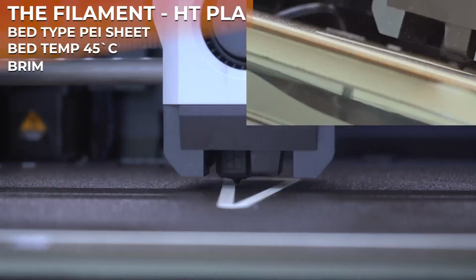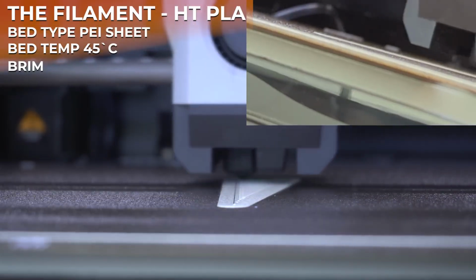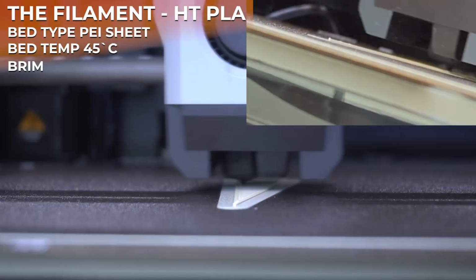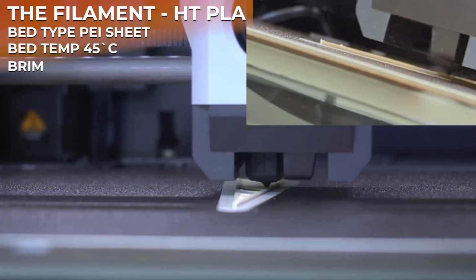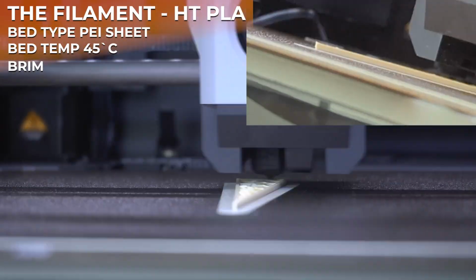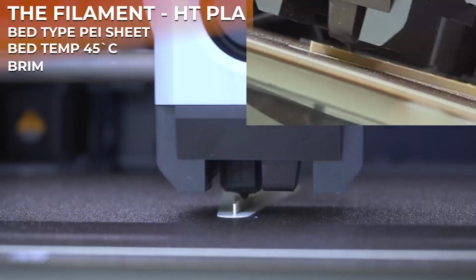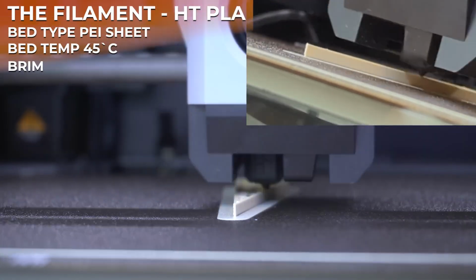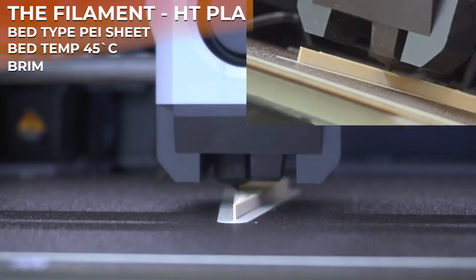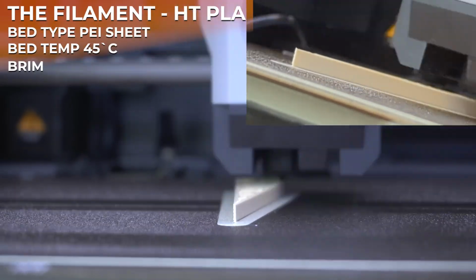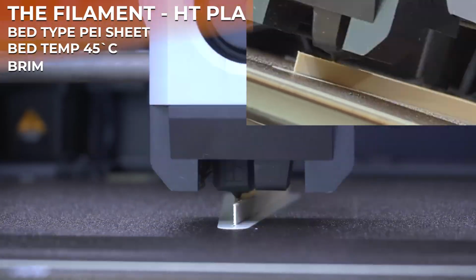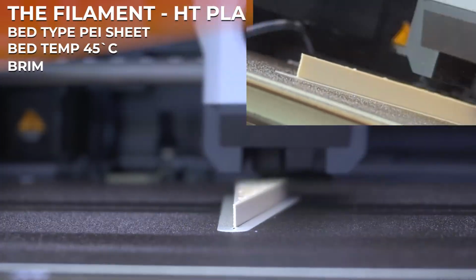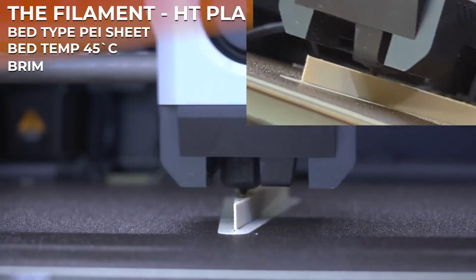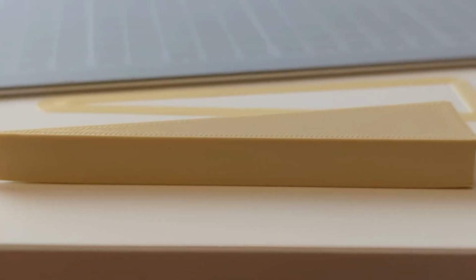Next up, we have still the same PEI sheet, bed temperature at 45 degrees Celsius, and this time we're using a brim. Fingers crossed, this time seems okay. Even halfway through, it seems like there is no warping. But again, at the front we can still see a little bit of warping. Inspecting the print, we can see the front warping as well as a little bit at the corner in the back.